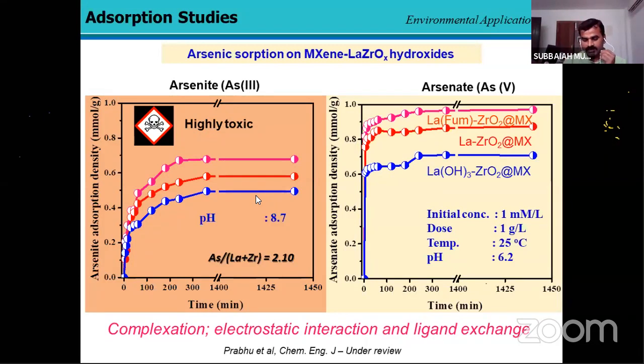Next we started with arsenic, since ions like hydroxide and oxide on the surface of an MXene material will be more helpful for adsorption of arsenite and arsenate. We started with different lanthanum and zirconium composite forms of MXene. We purchased commercial lanthanum hydroxide and zirconium oxide, which were intercalated on the MXene phase. It showed lesser adsorption capacity compared with other forms. Another form of lanthanum zirconium, synthesized by a simple one-step, one-pot method on the MXene moiety, showed higher adsorption capacity than the commercial phase.